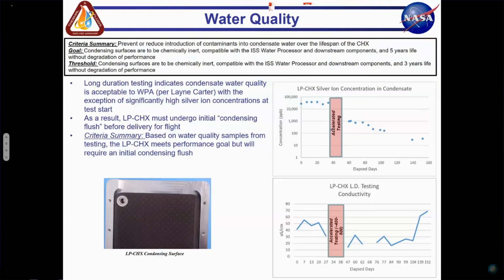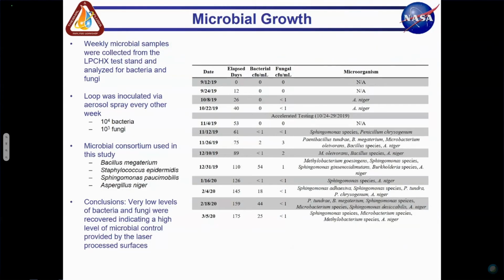So in order to solve this problem, it's too high a load for the WPA. So if we were to integrate this into the ISS, we'd likely have to do some type of initial condensing flush before we would deliver this over for flight on the ISS. But other than that, all of our water quality samples from our testing meet our performance goal. We don't anticipate that there would be any problems with this unit in terms of water quality to the WPA. Primary reason for that is because you're condensing on laser processed silver. There's no chemical coating that's used in this device.